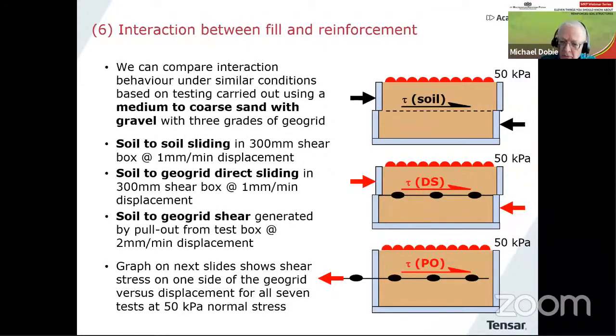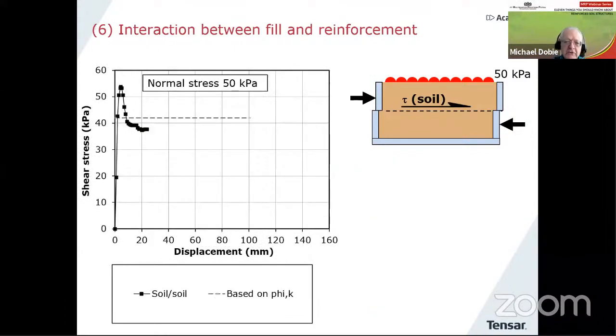And in this case, for all 7 tests, that's 1 soil test, 3 sliding interaction, and 3 pull-out tests, the one thing that's the same is that we have a 50 kilopascal normal stress. That's about 2.5 meters below the top of a structure. So here, I'm just showing the shear stress versus displacement diagram, but here is the basic shear box test on the soil where you see the peak value dropping down to the constant volume value. But we normally expect that in a well-compacted soil.